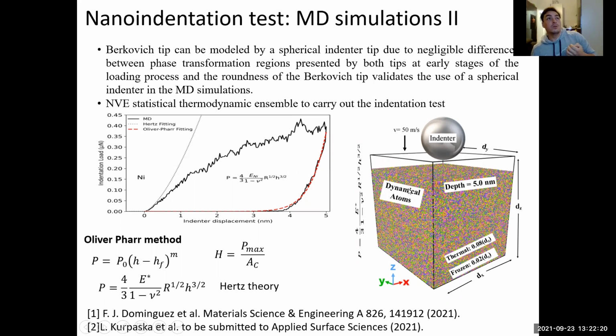And now we are going to apply some restrictions for the numerical modeling, where the bottom layers need to be frozen. Then we have the so-called thermal section, where a Langevin thermostat is applied to get rid of the heat added by the indenter tip and this push on the sample. The last part is the so-called dynamical atoms, where we run the MD simulation with an NVE ensemble. Because of the interaction of the indenter tip with the atoms, and also above the surface, we need to add the vacuum. Otherwise, we are not going to see the pileups here.